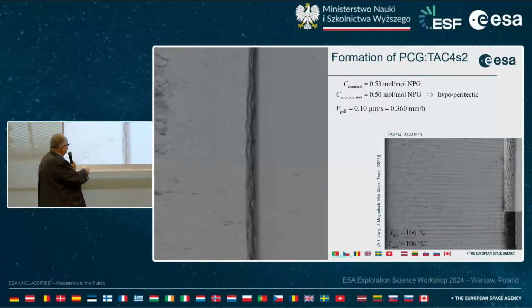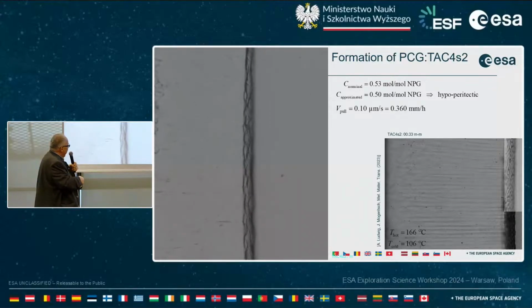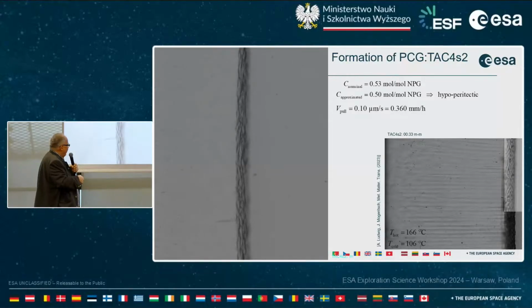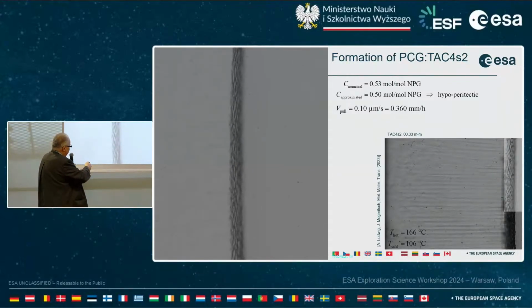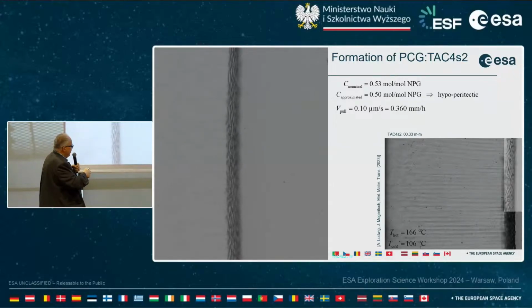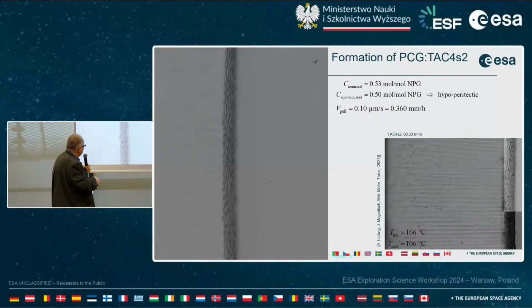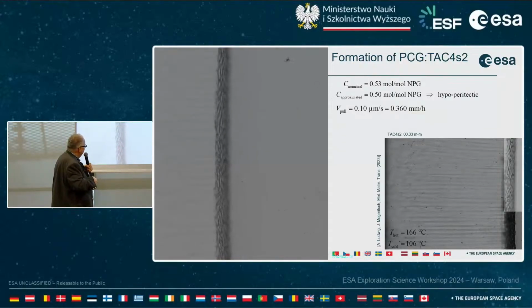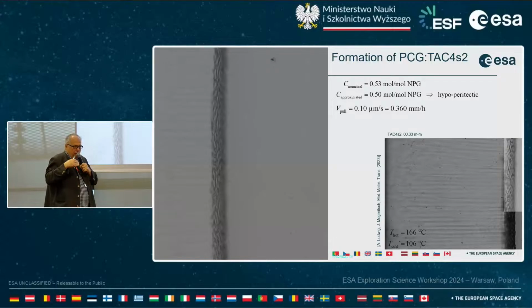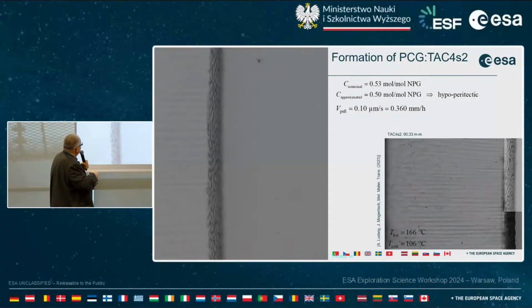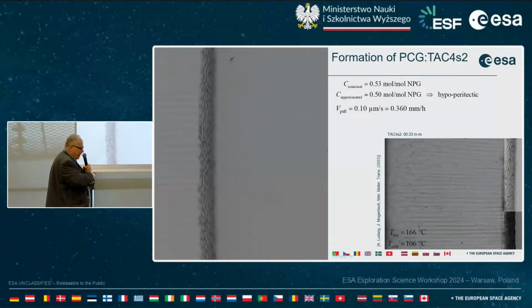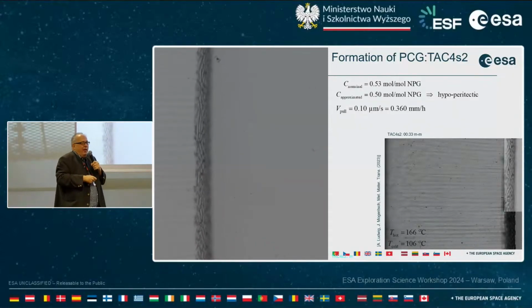Here it's liquid, it's solid, and from this NPG-enriched channel, the second phase comes like a wave in front. And as soon as it reaches the initial alpha phase, it builds this structure, and this structure changes during time. Without this decline of the liquid surface, we would only see a small black line and then these very nice alpha-beta phases.